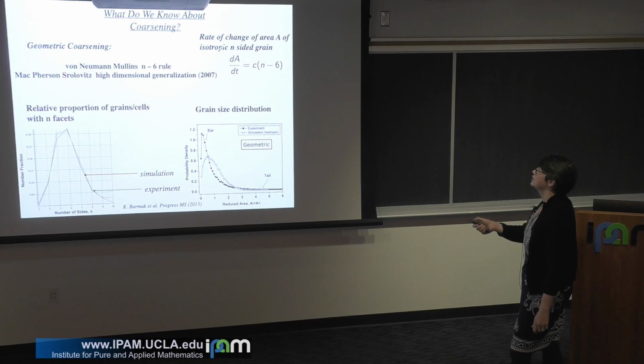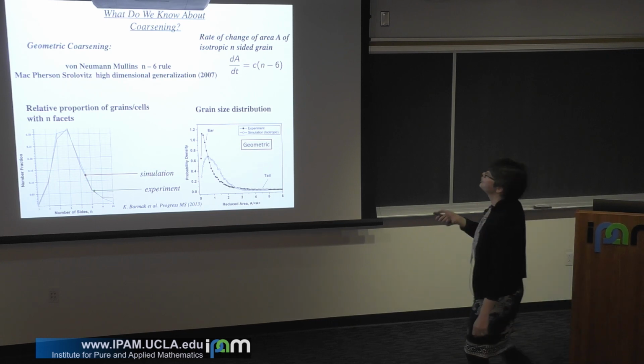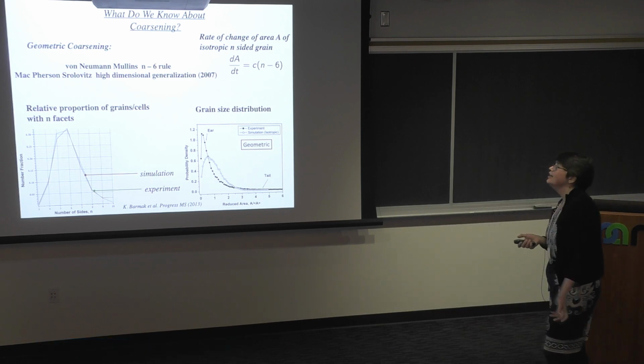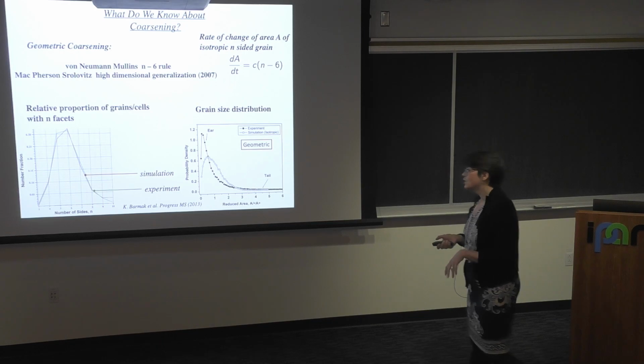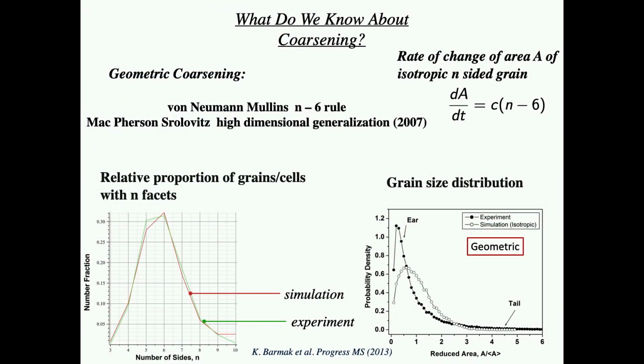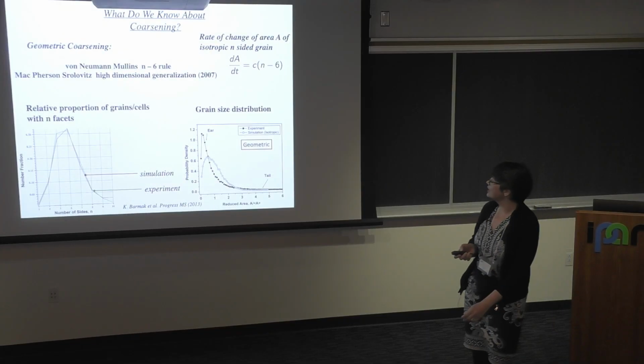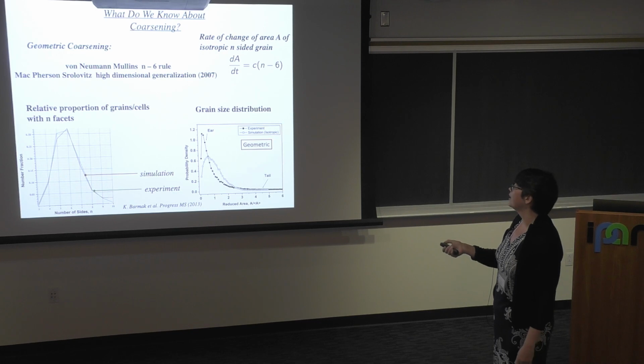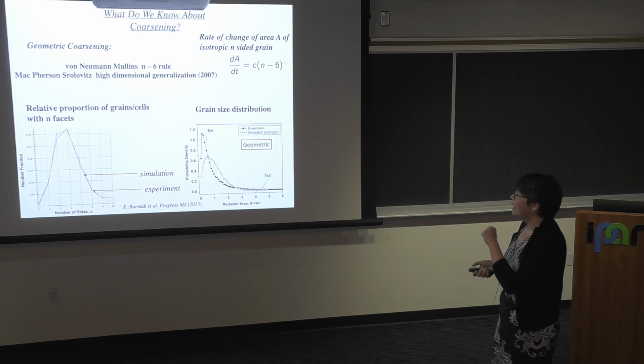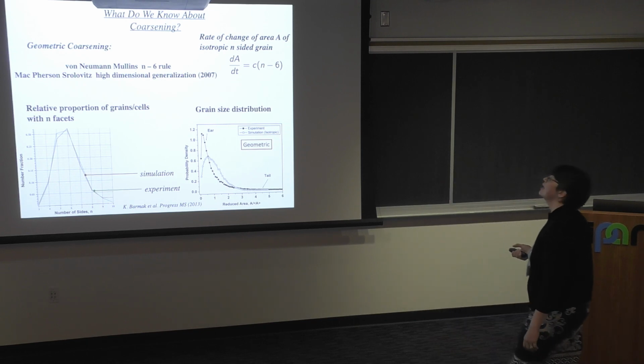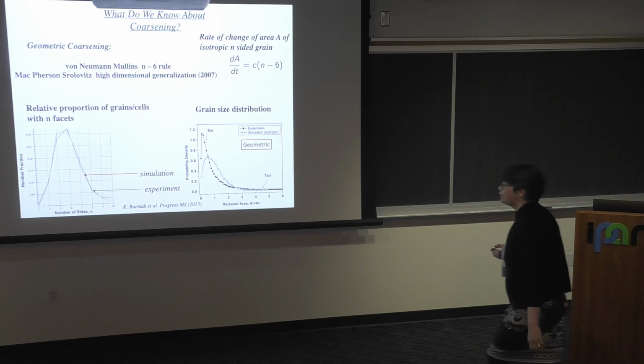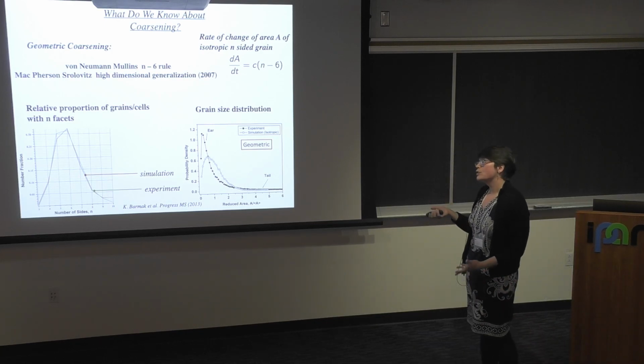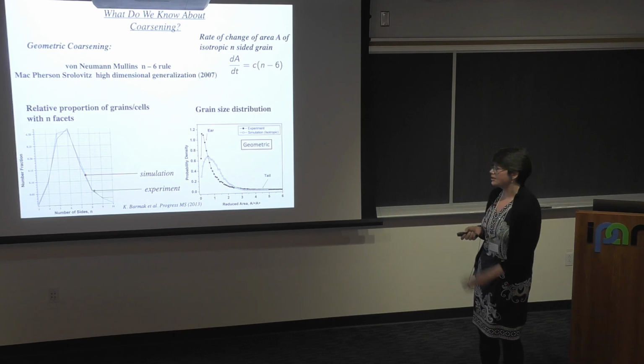which in 2 dimensions basically tells you that the rate of change of area of an isotropic n-sided grain is proportional to n minus 6. So on average, we expect that cells or grains with fewer than 6 sides will disappear, with more than 6 sides will grow, and with exactly 6 sides shouldn't really change. There are also generalizations of that rule to higher dimensions by MacPherson and Srolovitz, published, I think, in Nature in 2007. We can also look at different important statistical metrics of grain growth.